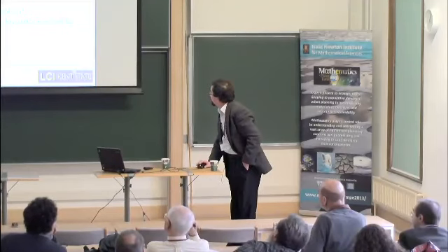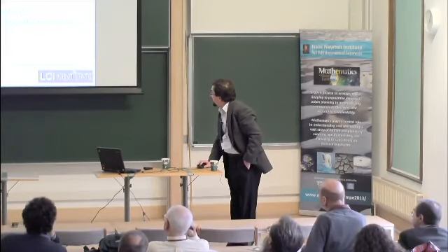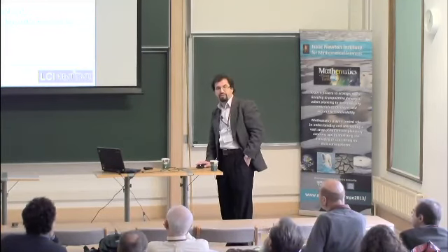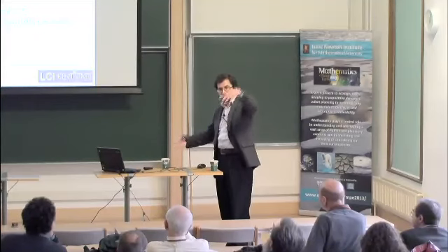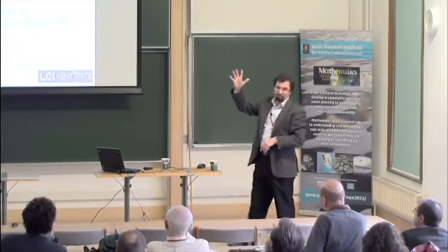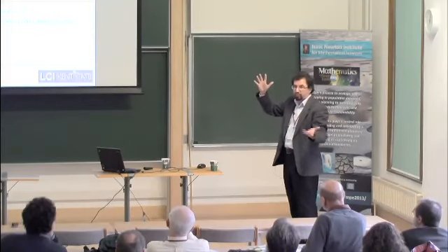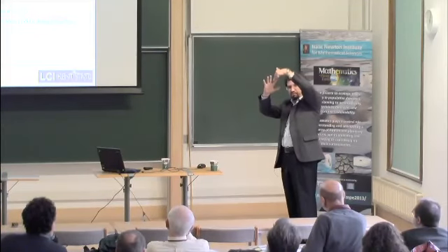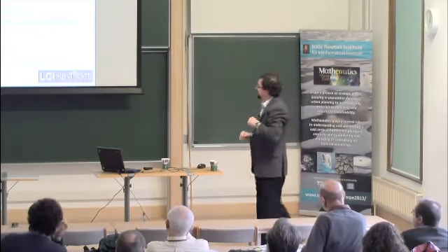So as shown by Bob Meyer, K1 should be proportional to the length of the aggregates. If I have infinitely long, say, polymer chains, then it's very difficult to create splay because I simply wouldn't have free ends to fill these empty places.